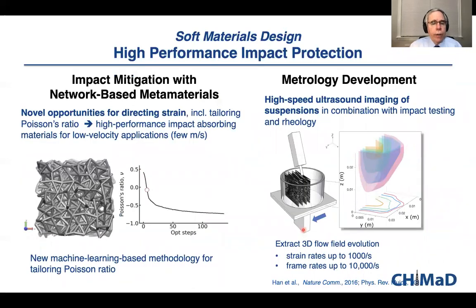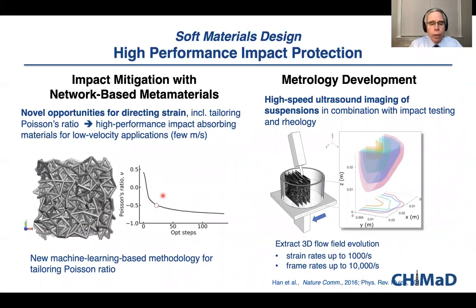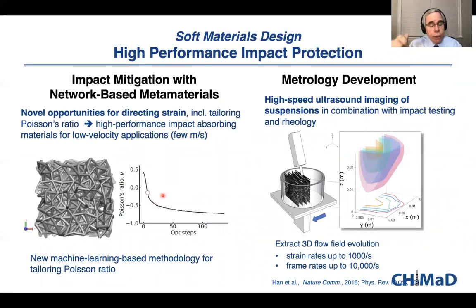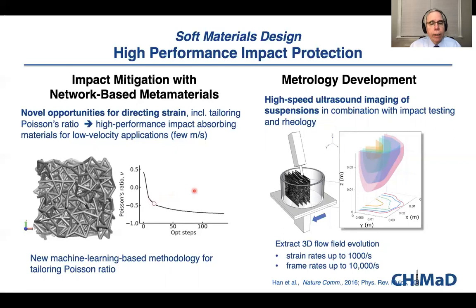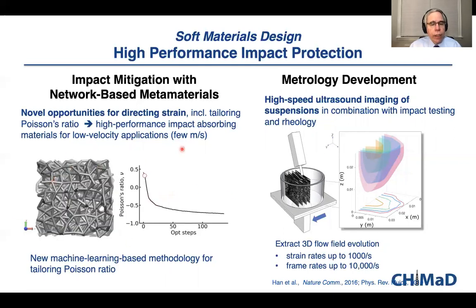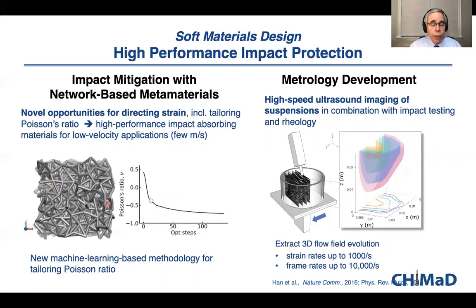And so the network-based metamaterials are focused on designing materials that have negative Poisson's ratio. These are auxetic materials where you push on them one way and they contract rather than expand like you might expect. And this is done by simulation, but they've also been able to show that the experiments find very similar behavior to that predicted by the simulations, calculations.